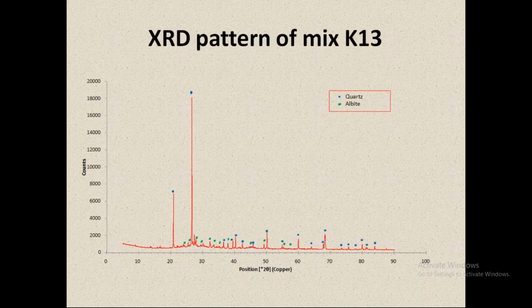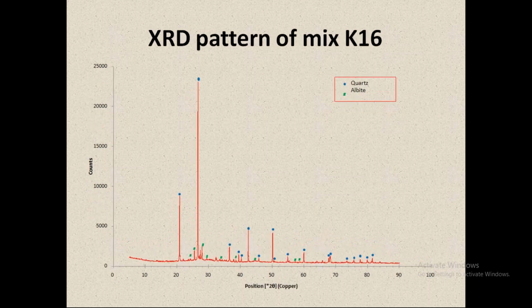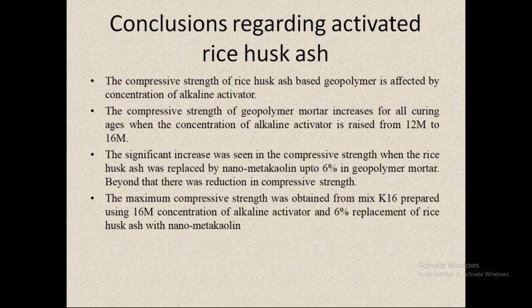This is as far as K13 is concerned. This is as far as K16 is concerned. So as far as conclusions regarding activated rice husk ash are concerned, the compressive strength of rice husk ash based geopolymer is affected by the concentration of alkaline activator. The compressive strength of geopolymer mortar increases for all curing ages when the concentration of alkaline activator is raised from 12 molarity to 16 molarity.